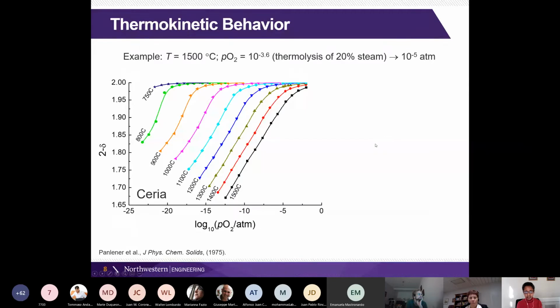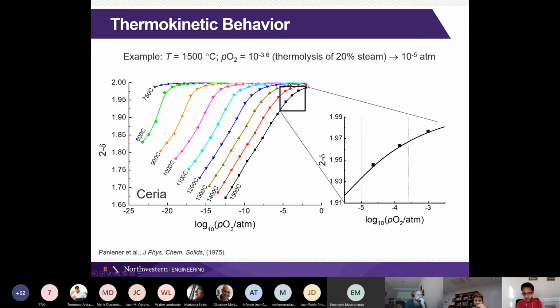Okay, so now let's imagine how this thermokinetic control can occur. So let's do our thought experiment with isothermal cycling, where we're keeping the material at 1500 degrees Celsius. We're imagining thermolysis at this high temperature with 20% steam, which gives us a moderate oxygen partial pressure of 10 to the minus 3.6. And we're doing reduction with our inert sweep gas, which has, again, this 10 ppm oxygen in it. Okay. So let's zoom in on this plot or this curve for 1500 degrees Celsius.